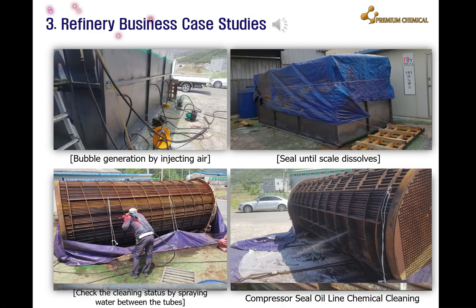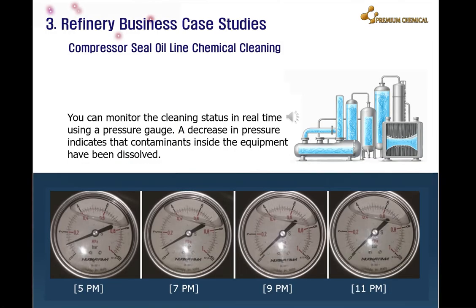Finally, to check the cleaning status of the heat exchanger, a pressure washer is sprayed between the tubes and the high-pressure water is discharged from the opposite side. This indicates that the scale, which was tightly trapped between the tubes, has been completely removed. If you want to check the washing status in real time, you can install pressure gauges at the inlet and outlet of the target equipment and check the washing status in real time through pressure drop or pressure.